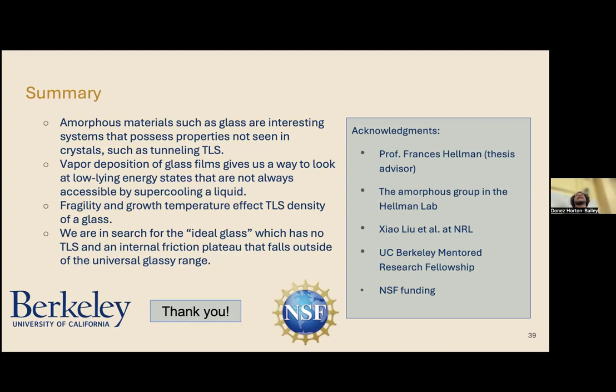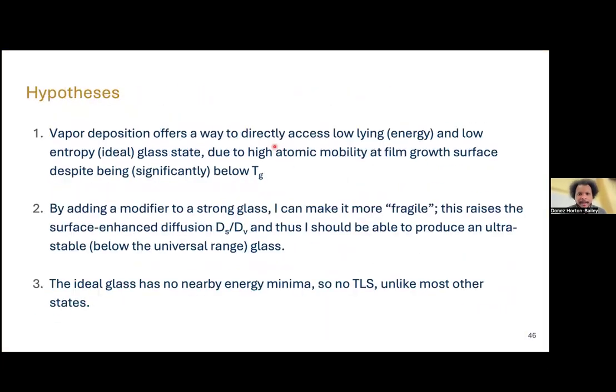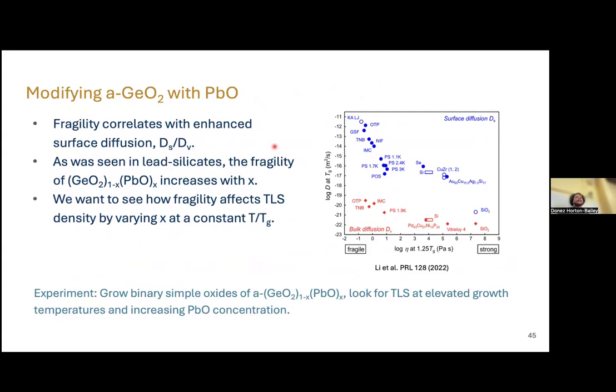Yeah, so the idea is that when you're growing a film, and I kind of skipped through this, but I may have a backup slide actually. Yeah, this kind of explains it. So there's this idea of surface diffusion and bulk diffusion. How well can the atoms within the film and on the surface of the film move? By elevating the temperature, you're able to increase the mobility. And the important thing is the ratio between the bulk mobility and the surface mobility. The surface mobility covers all the atoms that are coming in during deposition. The bulk is what's already there. So if you have a high surface mobility and a low bulk mobility, as the atoms are coming in, they're able to find their way around. And so we're able to tune that with deposition temperature.